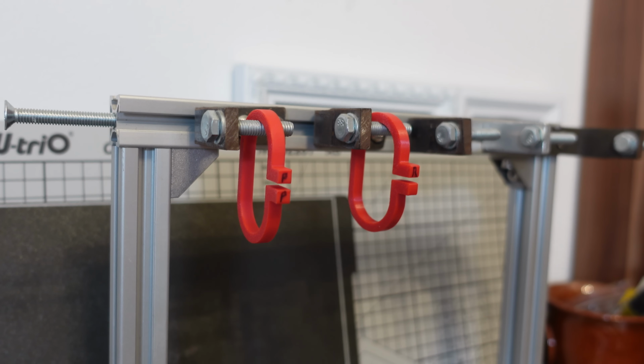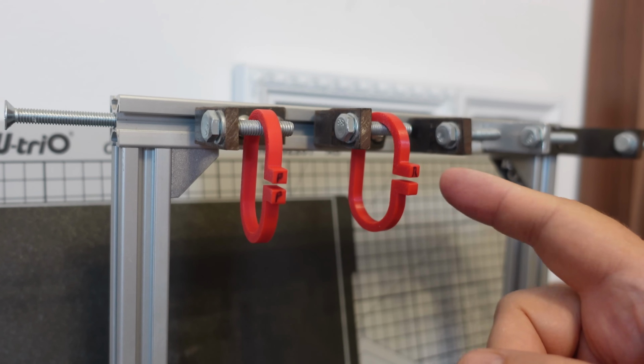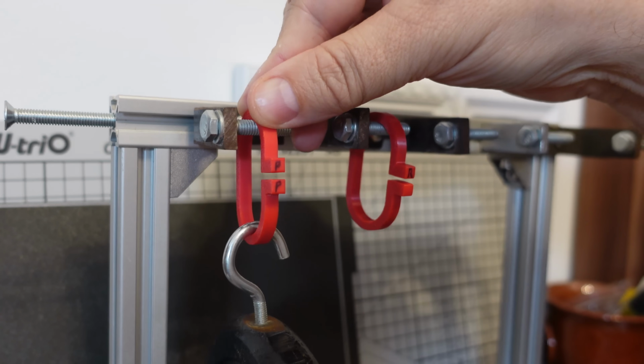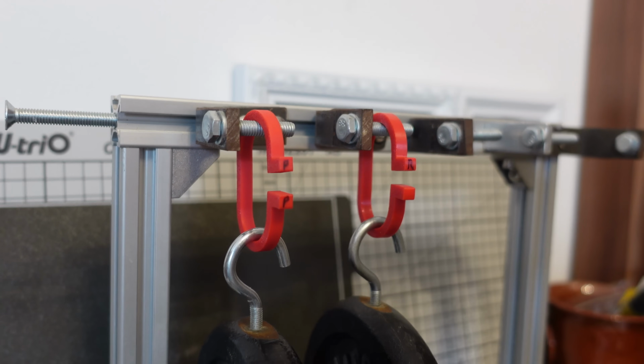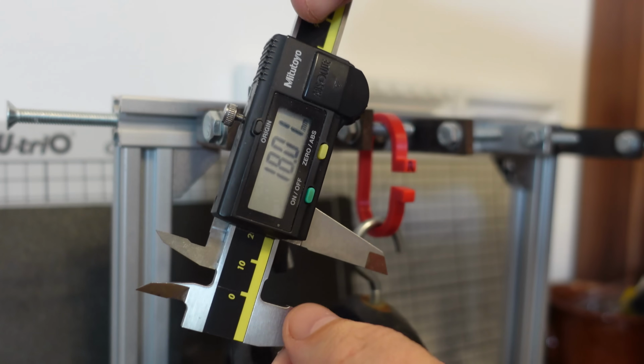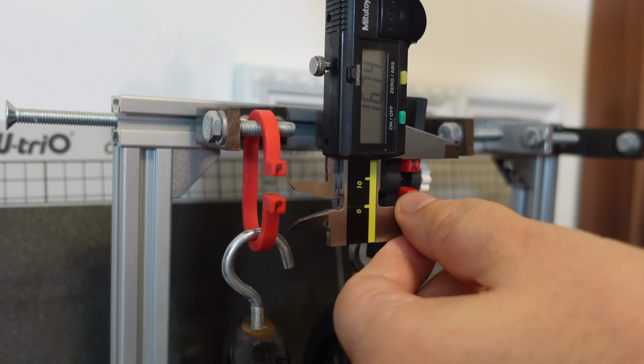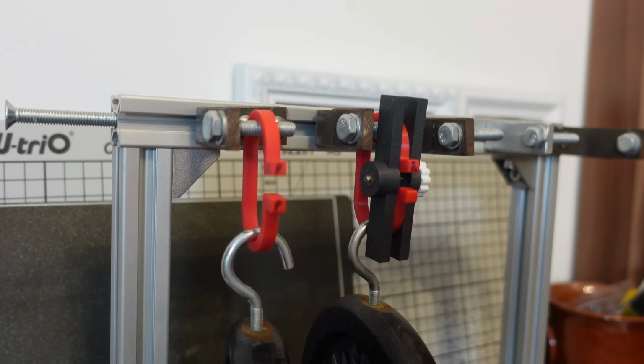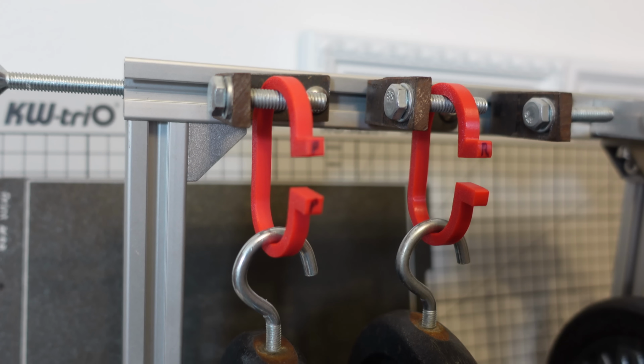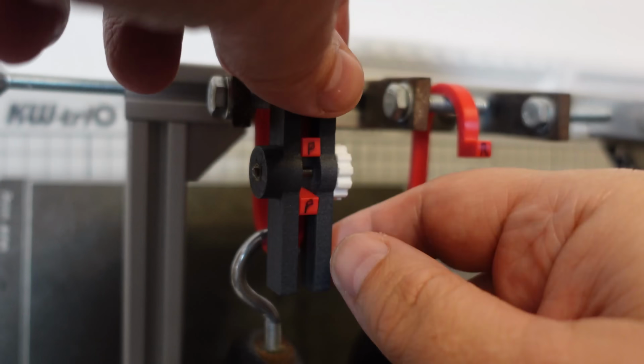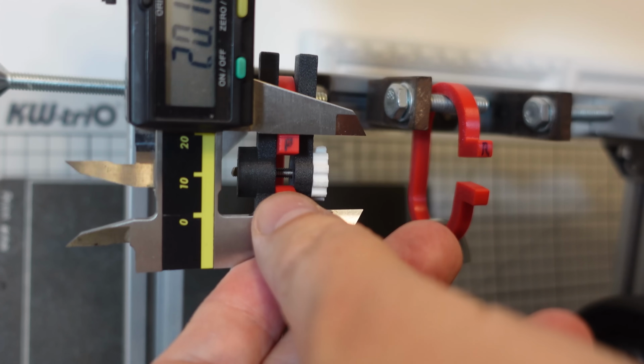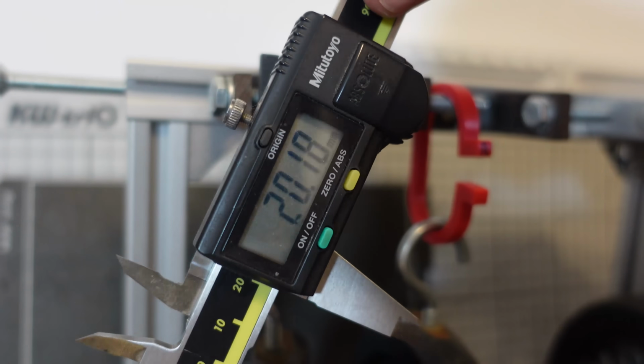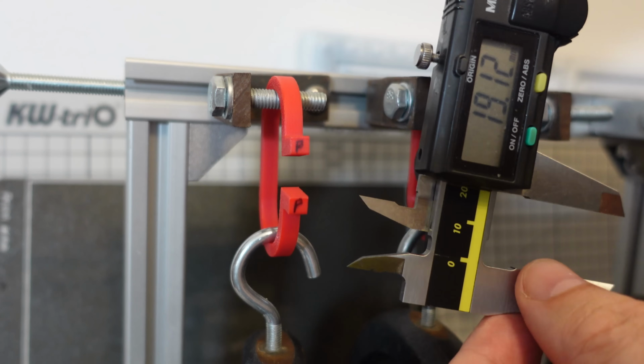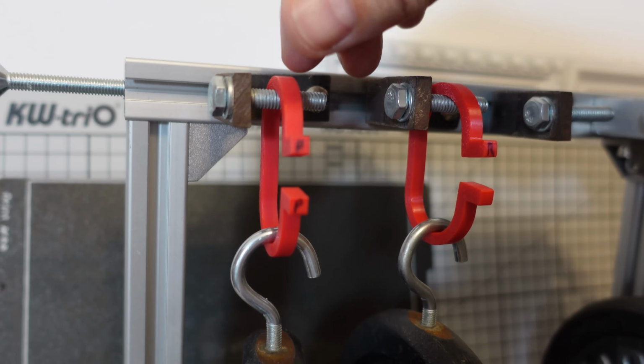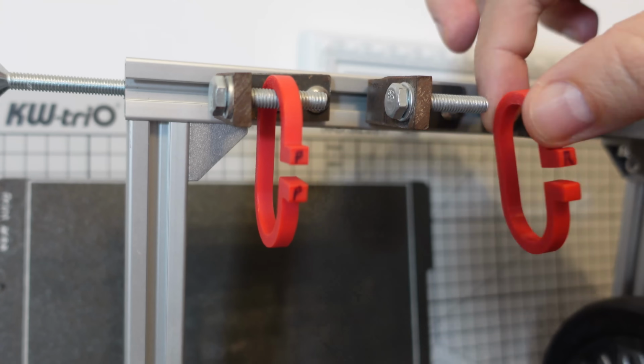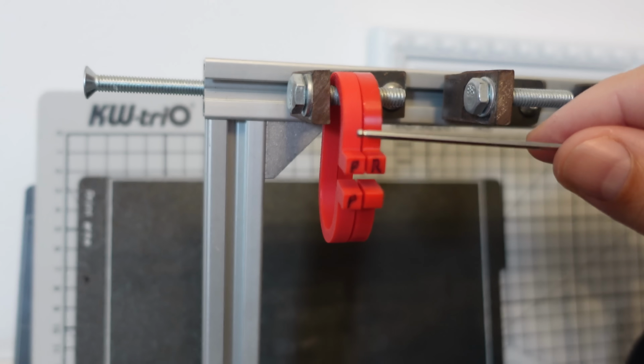Creep test, the deformation under the constant load. This is PETG Pro and this is rapid PETG. 18.01, 16.74, so a little bit more deformation on PETG Pro. The last 5th day, let's measure them again. 20.18, 19.12. Removing the load. And their permanent deformation is very similar.